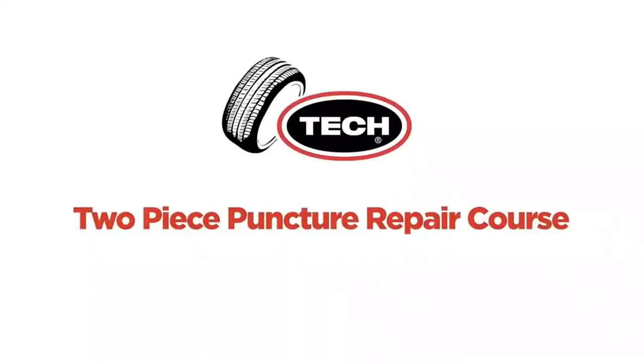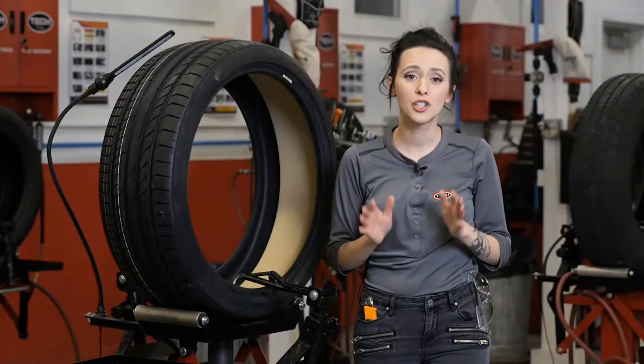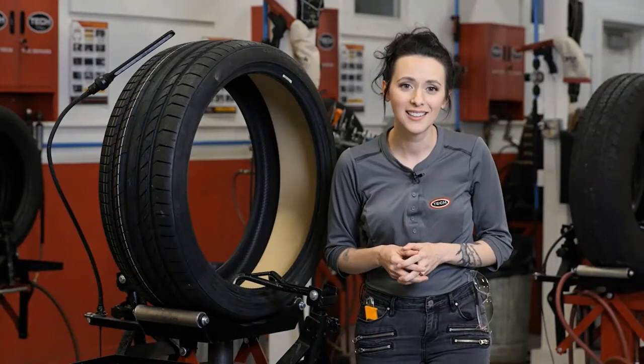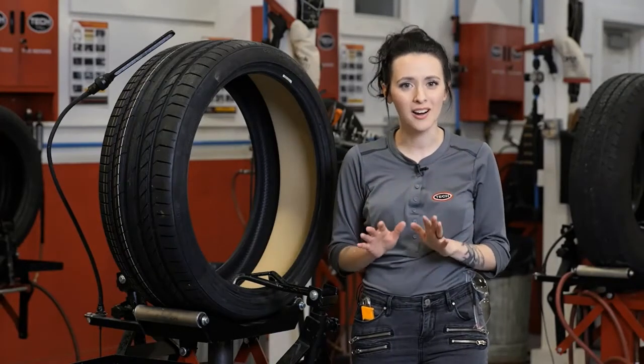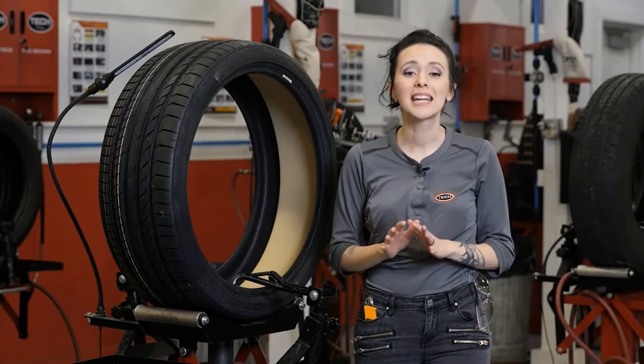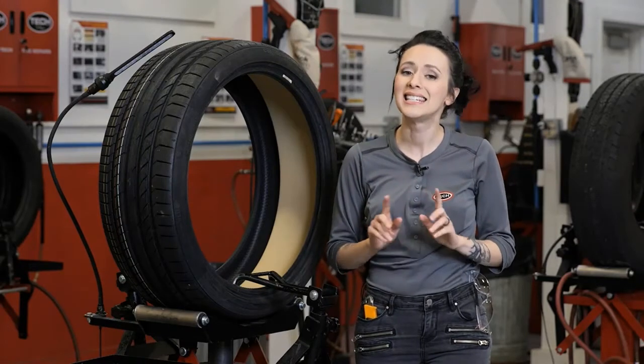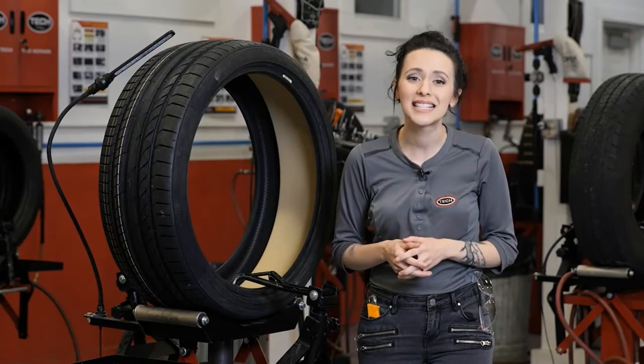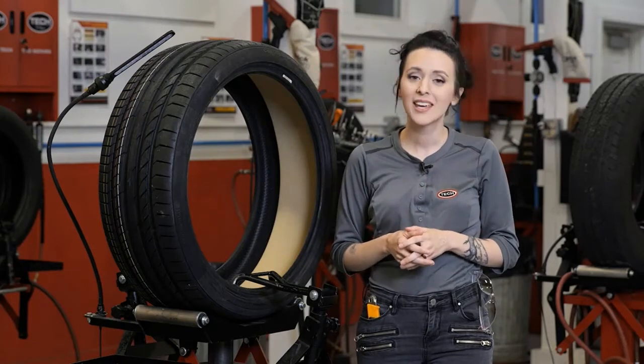A 2-piece repair should only be used if the adhesive used to apply the foam was a cured adhesive that can be buffed. If, however, the adhesive is extremely tacky, the tire may need to be replaced as a 2-piece repair is not recommended. Refer back to Tech's training course on 2-piece repairs if you need a refresher on this procedure.